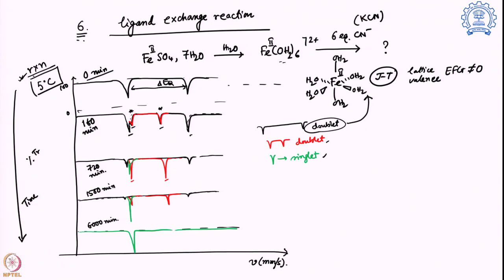To understand that, we have to understand what is actually happening with this iron hexahydrate sample when it is reacting with cyanide ligands. What we have found is that in the beginning, it reacts with 6 cyanide altogether and creates this molecule. This is in iron 2 state, so overall charge was plus 2 in the beginning. Now it is still in plus 2 state, but now